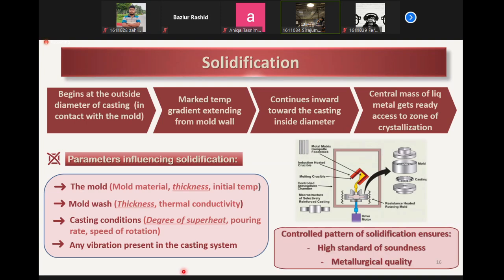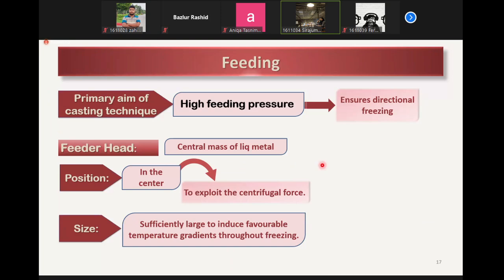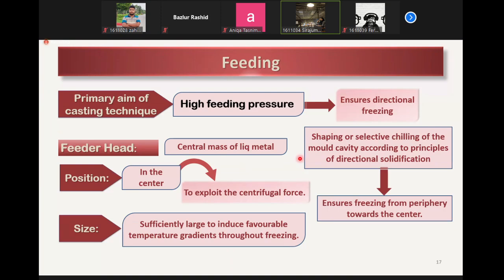Control of the pattern of solidification is very important as casting soundness and metallurgical quality greatly depend on it. As high feeding pressure is a must for directional solidification, obtaining this is the primary aim of casting technique. To take the full advantage of centrifugal force, mold cavity must be shaped or selectively chilled according to the principles of directional solidification to produce solidification from periphery towards the center. Basically, central mass of liquid metal does the function of feeder head used in static casting. So it is positioned at the center and is sufficiently large to induce favorable temperature gradient.